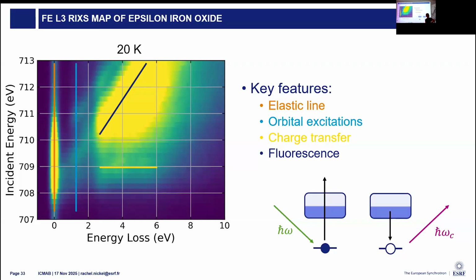Okay. So this is one of the big questions about this material. In a normal material, you're absolutely right. It should be Raman-like. We should see clear vertical streaks that are running down from transitions. However, because the cross-section of the transition changes, it won't be a discrete line that shows up throughout the entire excitation region. Here we have a couple overlapping features.